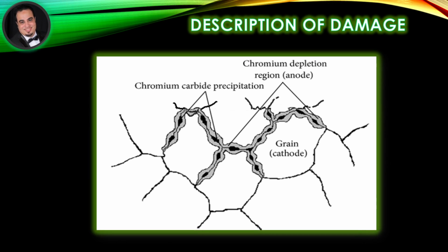As illustrated in the figure, when ferritic stainless steels are exposed to the temperature range of 600 degrees Fahrenheit to 1000 degrees Fahrenheit, fine, chromium-rich precipitates segregate at grain boundaries. Grain boundary segregation of the chromium-rich precipitates increases strength and hardness, decreases ductility and toughness, and changes corrosion resistance.